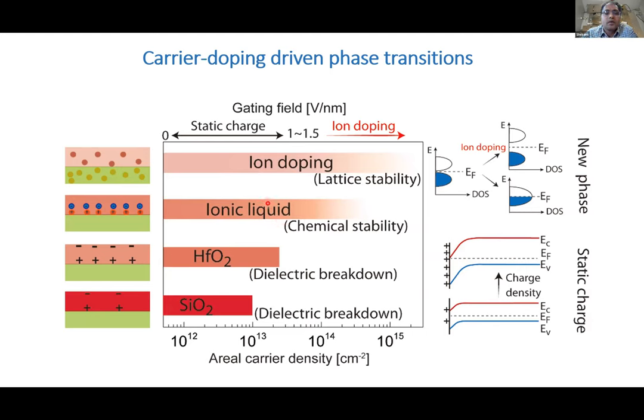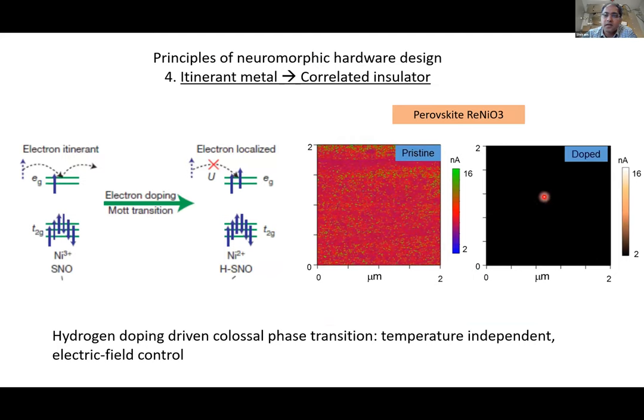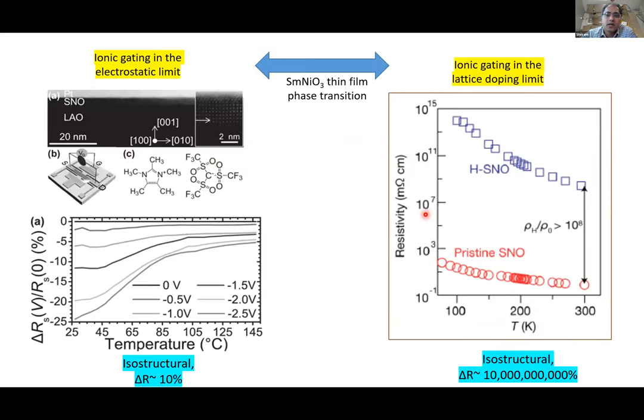And then if this is not a good system for using electric double layers because of chemical stability, then we can literally exceed this all the way to the lattice stability limit by ion doping. So this is what we are doing in these cases, where we are introducing dopants of the order of one carrier per unit cell. At this level, you can completely reconstruct the bands and discover new phases that you simply did not know existed before. So between pristine nickelate and this phase here, the only way to discover this is by adding electrons at this level, right? So this summarizes about 10 years of research in our group.